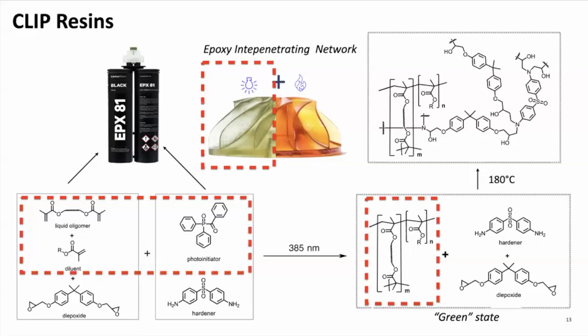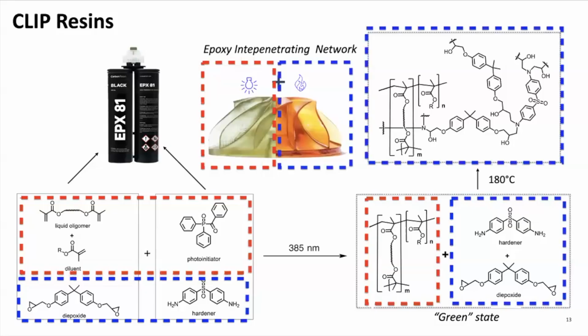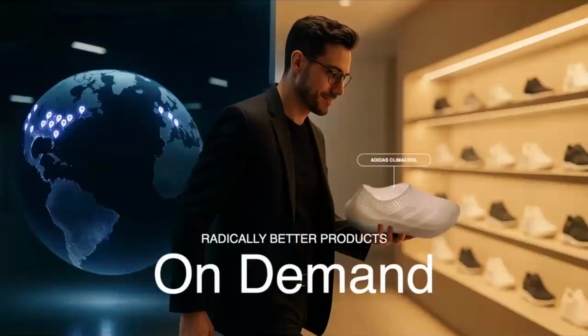So we'll print a part, and it's mechanically not very strong. It's fairly weak. And then we get the excess resin off the part. And then we induce the second stage chemistry, here epoxy chemistry. And it's basically a solid state polymerization in the form of the part. And that's how you get great material properties. So we basically broke it into two problems. Shape the part with light and do a second stage solid state polymerization. And this works like a champ. And this is how we get amazing properties in lots of different areas. And so I want to just quickly show you some products. Adidas running shoes. There's another great video here.